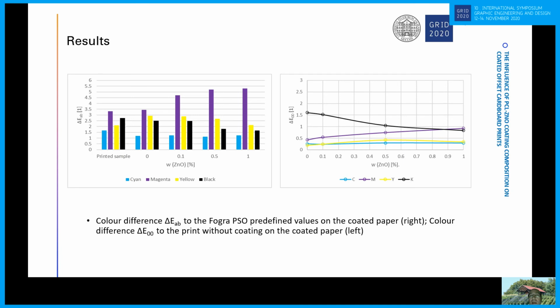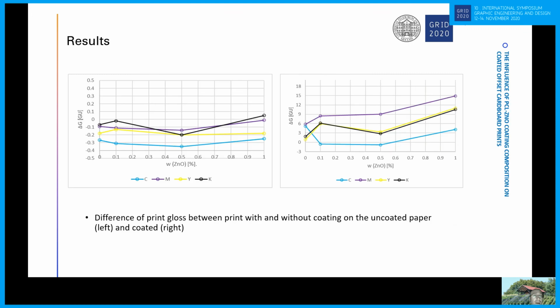the 1% of zinc oxide. This is leading really to some acceptable changes in the variations in the predefined FOGRA PSO values, while we can see that magenta is on all samples really high, and in samples with 0.5 and 1% of added zinc oxide nanoparticles is outside the defined standard.